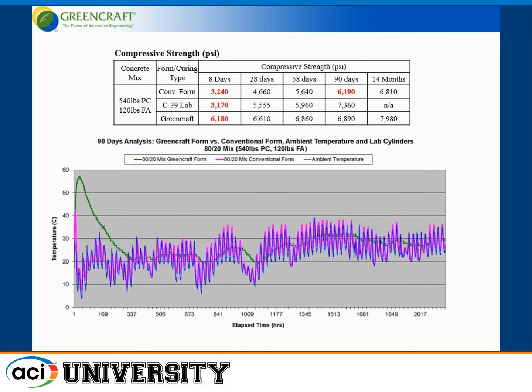And another thing is that if we kept the concrete insulated for its life, the green line that you see here barely moves up and down a couple of degrees Celsius a day, even though the ambient temperature moves, you know, 20, 30 degrees a day. So we eliminate the early thermal shock, and eliminate the thermal stresses for the life of the structure if we kept the concrete insulated for its life.